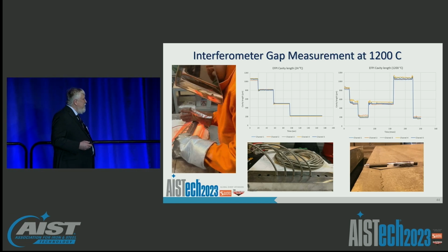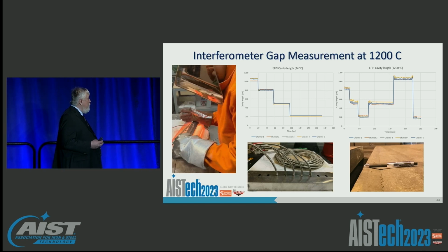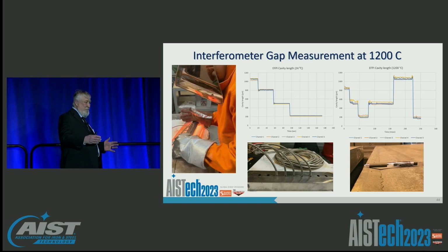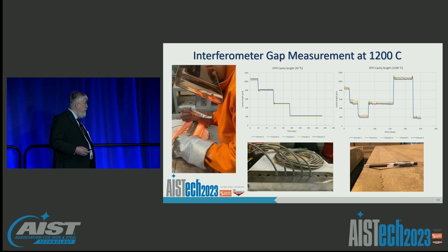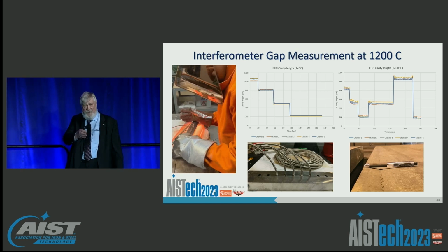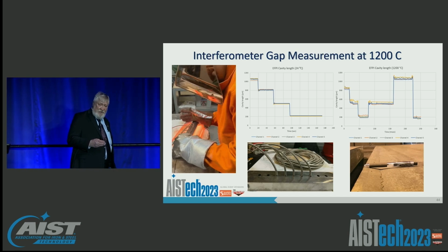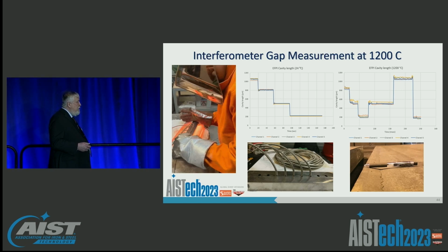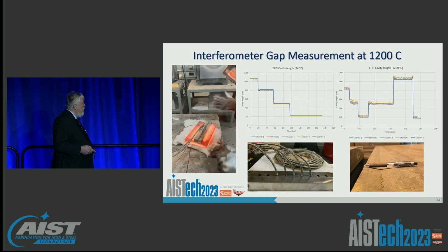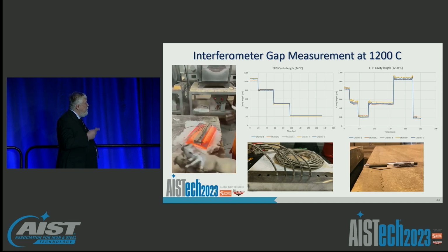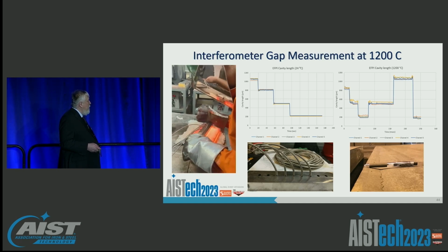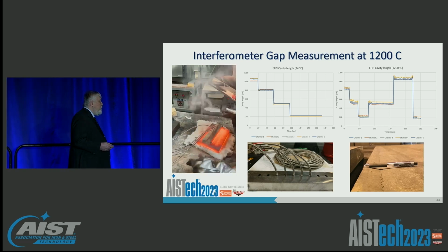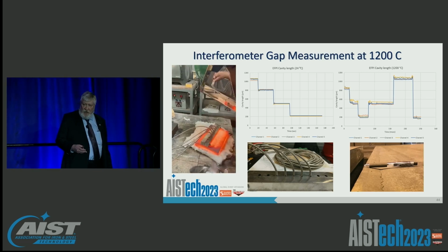So here are some measures. The other thing we're thinking for these interferometers is that they potentially have a lot of value for doing measurements in the caster in the future. Not only can we monitor slab shape and other things directly exiting the mold, but we also potentially can use these for measuring things that Brian would be really interested in, such as inner roll bulging behavior. And these sensors, because of their temperature insensitivity, could be a really good candidate for this. The other thing that we're actually exploring, this is just a high temperature calibration showing the measurement of a calibration block at 1200 C versus room temperature, just showing that we get the same measurements regardless of the environment temperature.